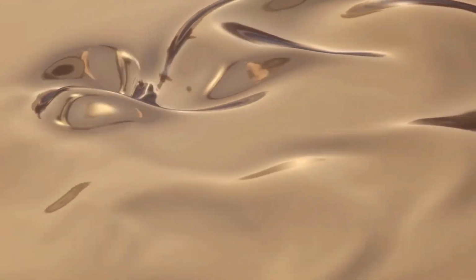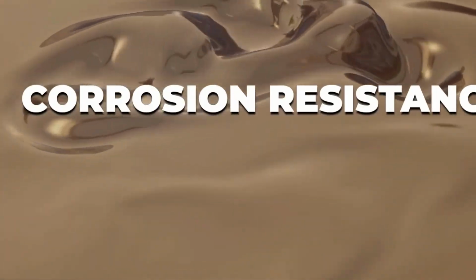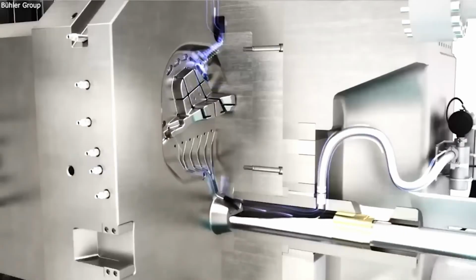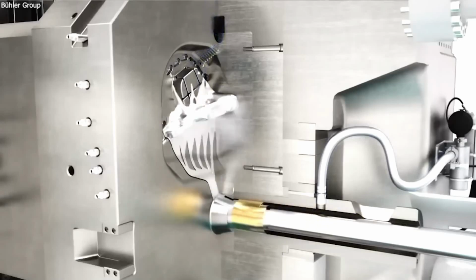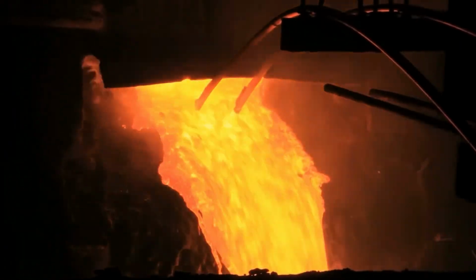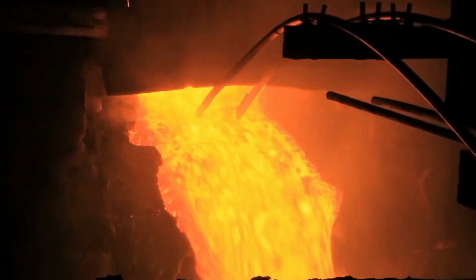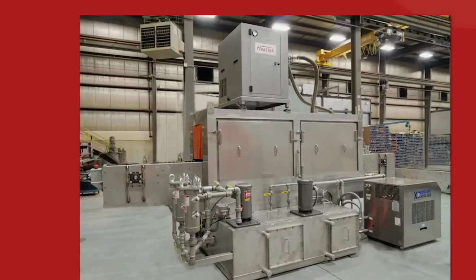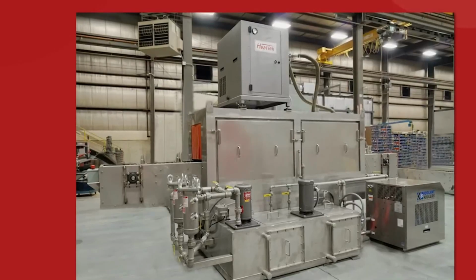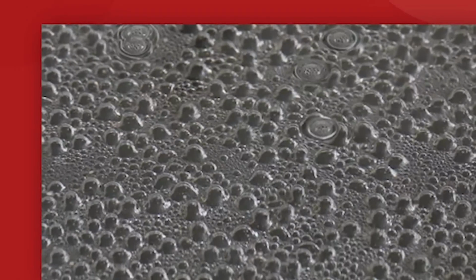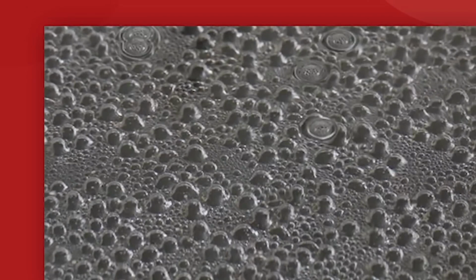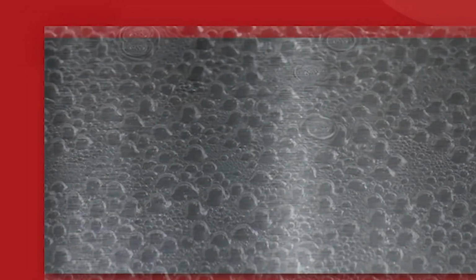The Giga casting alloy prioritizes not just strength, but it also has to flow smoothly in liquid form, have incredible corrosion resistance and ductility. The enhanced flowability of the alloy means that Tesla does not have to perform a heat treating process on the Giga castings after they come out of the die. Other large castings require a few hours of baking in an oven to soften the metal and collapse any small air pockets or porosity that may have developed inside the structure.